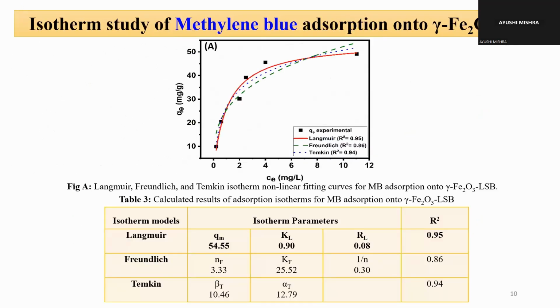We have also studied the isotherm of the adsorption process, and as we can see clearly, it follows the non-linear Langmuir isotherm model, which shows it's monolayer adsorption. With the R square value closer to 1, at 0.95, it gives a Qmax value of 54.55 milligrams per gram. That's the maximum adsorption capacity of the adsorbent.